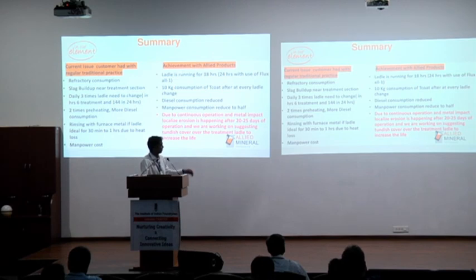But here, after 20 to 25 days we had a localized erosion where the metal was impacting on the floor, and we are working with the customer to have a tundish cover on the top for the treatment to reduce that erosion in that area and increase the lining life.